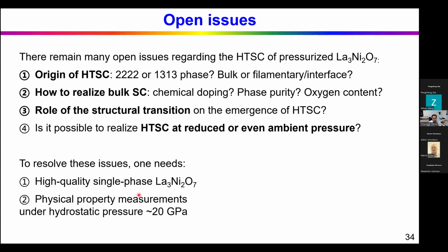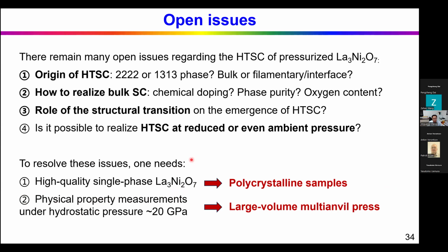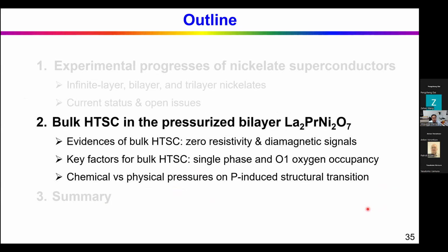And also, as I mentioned, the transport property is very sensitive to the pressure environment. So we need to measure the physical properties under hydrostatic pressures up to 20 GPa. To address these issues, at the beginning we started with single crystals, but we found it pretty difficult to figure out what's going on because of sample quality issues. So we turned to polycrystal samples, and we use the large volume multi-anvil press. So in the second part, I will present our results.